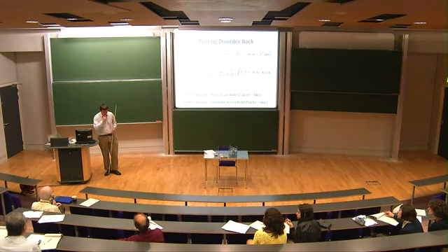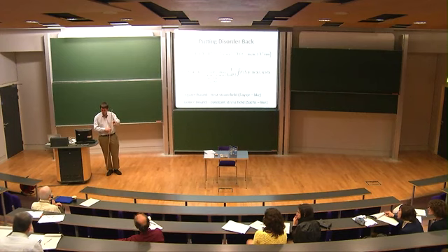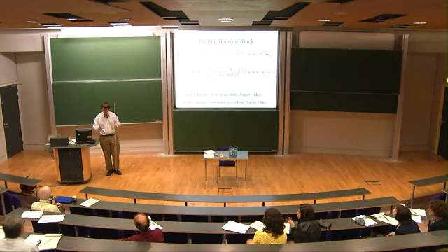So I guess the point I was trying to make is because you break the symmetry after you've put that in, they will. I don't know whether the A to C transition is self-accommodating, right? But when you go through that transition, it might locally make some complicated texture pattern on a much smaller scale. So you get a region where the symmetric A was effectively homogeneous. But on the transition, you'll get a much finer domain structure driven by kinematic compatibility.